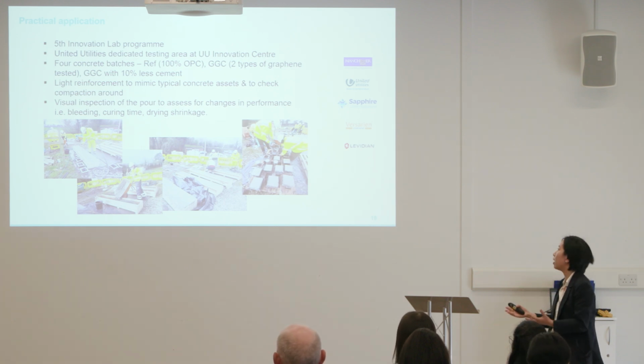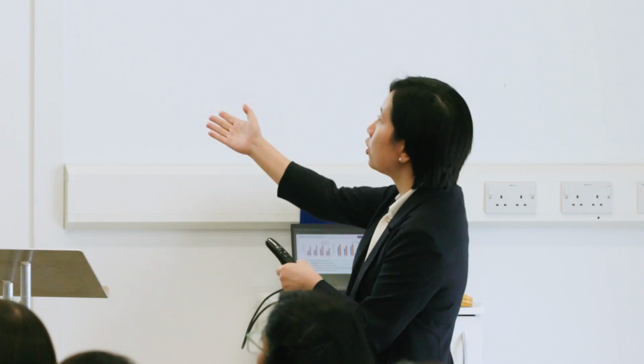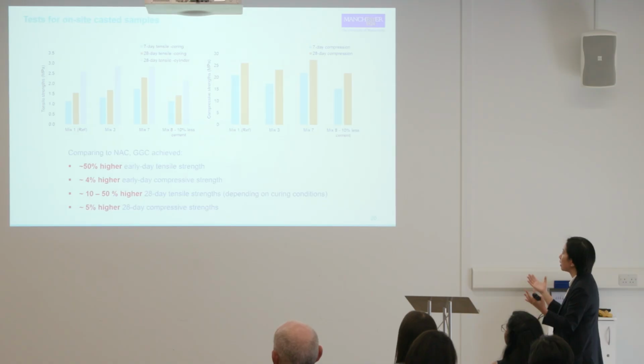compaction around the rebars. After the casting, we did some visual inspection of conditions like bleeding, curing, and drying shrinkage. We also, after 7 days, 14 days, and 28 days, did some coring to get the cylinder samples from those on-site large-scale specimens. So these slides show the results that we've got from some of the coring specimens and also casting specimens.